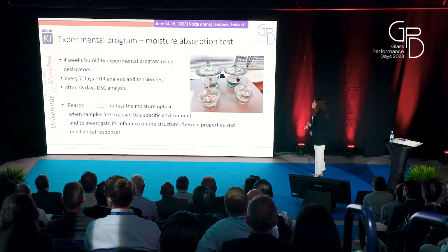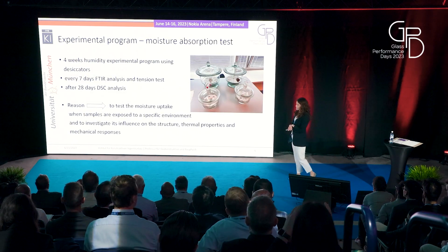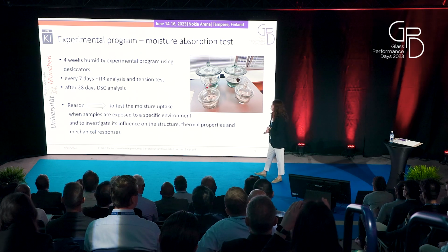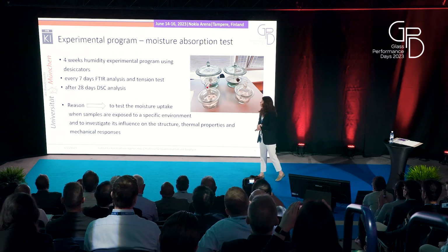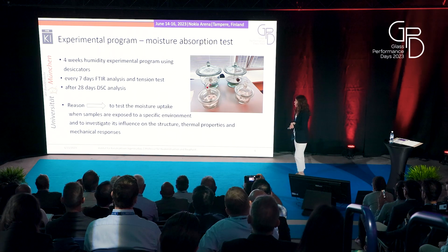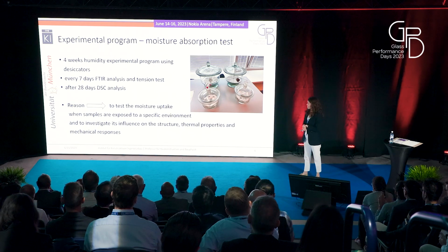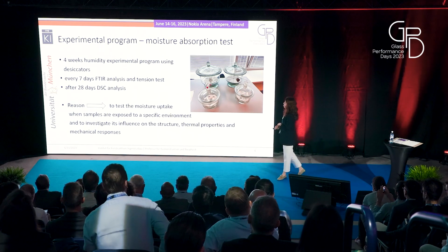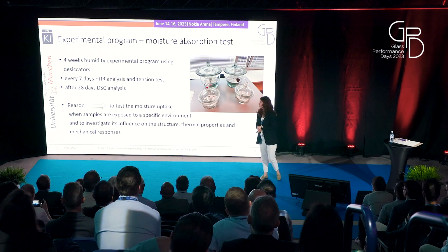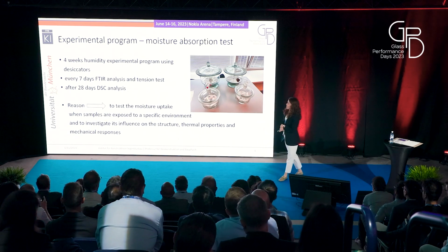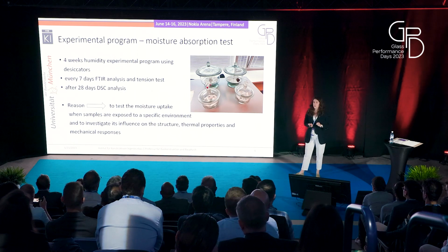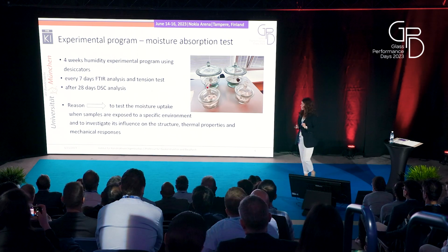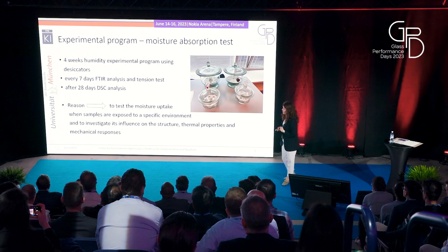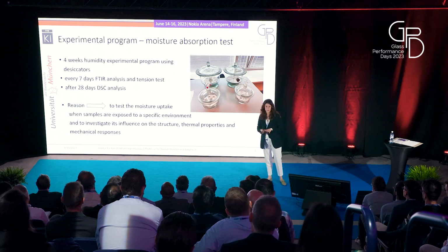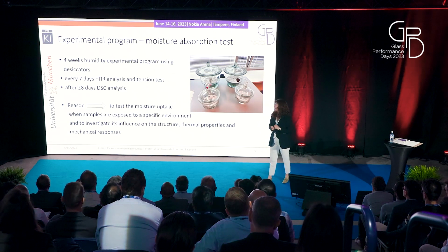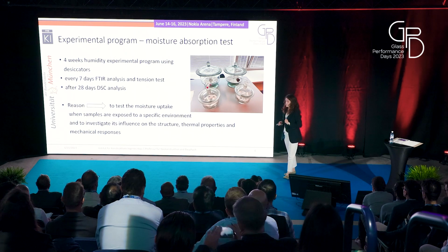So now I will show you the experimental program that we provided. We started with this moisture absorption test. We did it for 4 weeks. In this humidity experimental program, we placed our specimens into desiccators, and every 7 days we did the infrared spectroscopy and also tension tests. And after 28 days, after 4 weeks, we also did the differential scanning calorimetry.